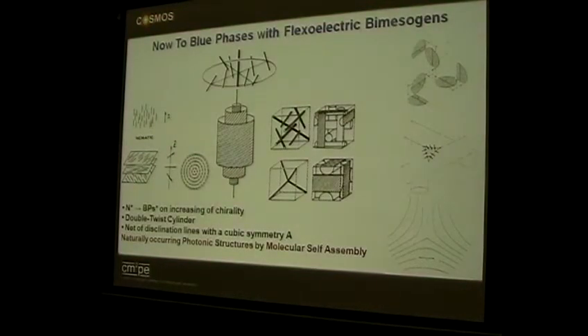But you've got twist around the system. And what happens with these funny, peculiar double twist systems is they form cubic lattices of disclinations. I've drawn that over there. When these cubes form, or the structures form, you get areas where you can't get alignment, where the director doesn't know which way to go, right in the center there, and you get isotropic material. Now, it turns out that isotropic material is what gives you the S equals minus a half disclination line, but it's also incredibly important if you want to form a stable blue phase.